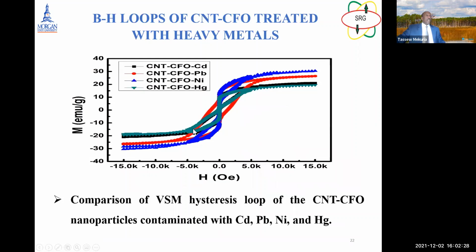Okay, and we also compare the others together: the comparison of the VSM hysteresis loop of the CNT-CFO nanoparticles contaminated with cadmium, lead, nickel, and mercury. For mercury we see a little difference, but most of them are not that significant, and still not well studied. So our focus is only on hexavalent chromium, but this is still a juvenile kind of report.